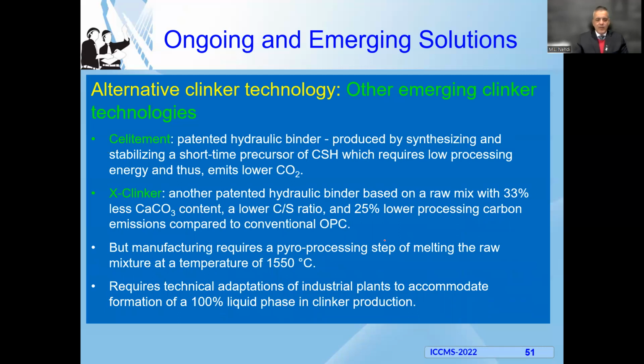And then there are other ones. For example, Celitement, a patented hydraulic binder. Here we synthesize a precursor of calcium silicate hydrate that requires less energy and emits less CO2. And then there is the X clinker, but this is quite different. It's quite a unique process, as we will need to essentially melt the ingredients through pyroprocessing, and therefore even the entire technology of producing cement needs to be adaptable to that. When you melt the mixture, the existing technology may not be suitable. In addition to this, it requires higher temperature.